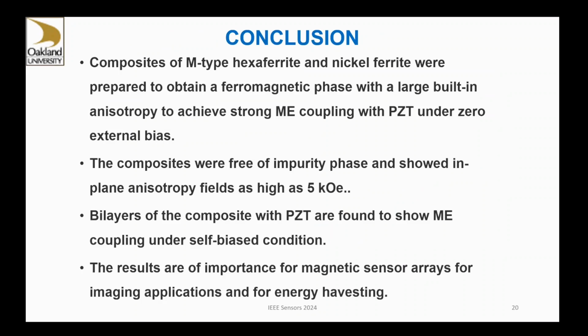So to conclude, we are able to make essentially defect-free composites of hexaferrite and nickel ferrite. And these have very high magnetostriction as well as a built-in bias magnetic field that could be utilized to put together magnetoelectric magnetic sensors, of both AC as well as DC, potentially for imaging applications such as magnetocardiography. There's a lot more work to be done on this because the overall voltage response is rather weak.